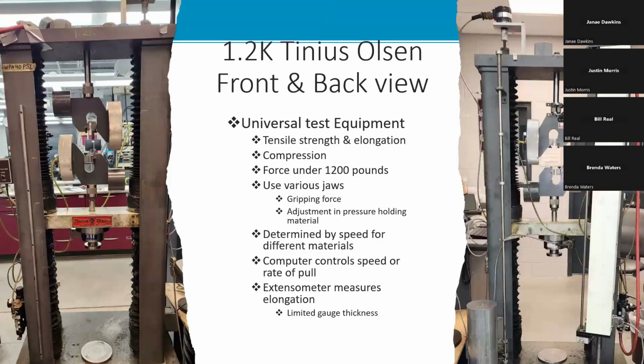How do we test for tensile strength and elongation? So this is your 1.2 K Tinius Olsen, and it's just a front and a back view. It's a universal test equipment, what mostly everyone uses to test tensile strength and elongation. And you're looking at compression. Since it's 1.2 K, you're looking for force that's under 1,200 pounds.